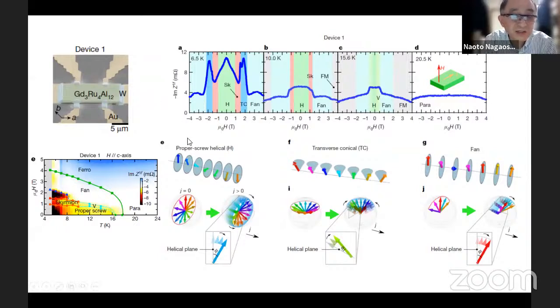So these are experimental results. And here is a cartoon, and here is the experimental result. And as you can see, in this helix phase and the transverse conical phase, the imaginary part of the impedance shows large values. And in the normal state, paramagnetic state, you only have a background. And ferromagnetic state, you don't have. So then this inductance is coming from the helix structure. And in the fan state, this angle of noncollinear spin is reduced. So that's why the signal is also reduced. So all these are rather consistent with the picture of emergent electric field associated with the noncollinear spin structure.